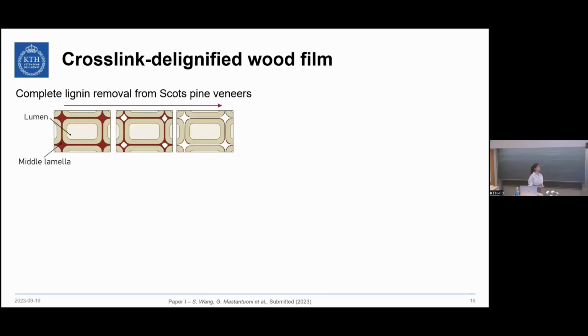However, softwood especially can be very sensitive to extensive delignification. The reason is that the more we remove lignin, which is in the middle lamellar region, a lignin-rich area, the more we progressively remove the glue that keeps the fibers together. So if we push the delignification too much, the structure will tend to fall apart.